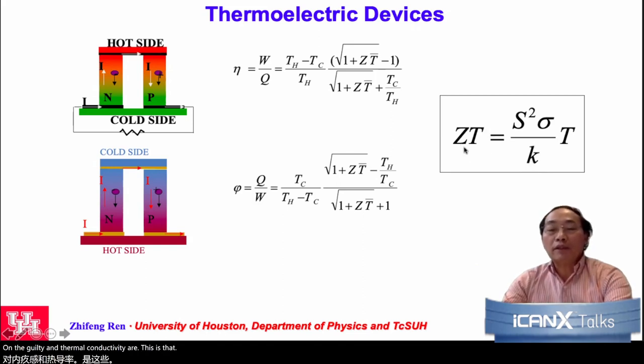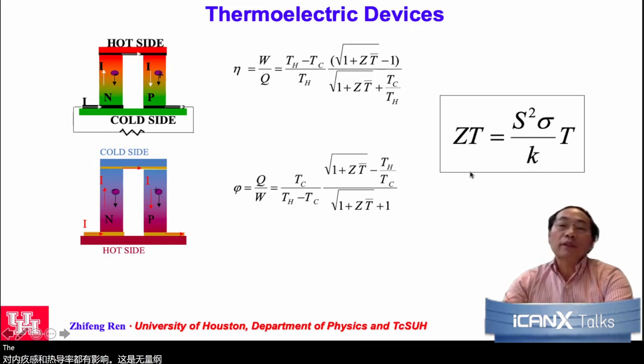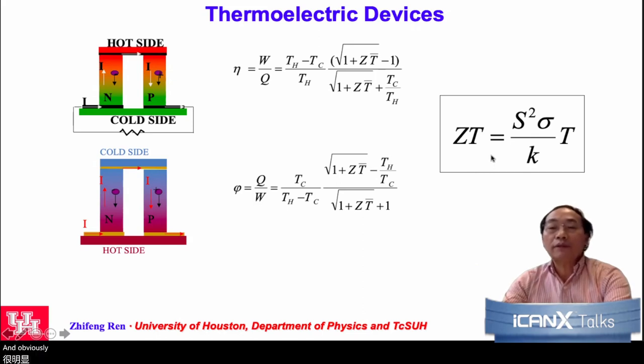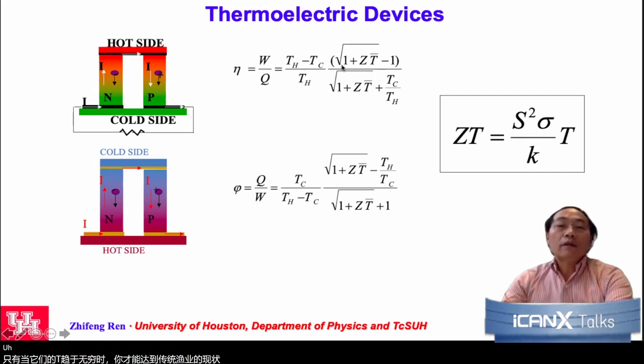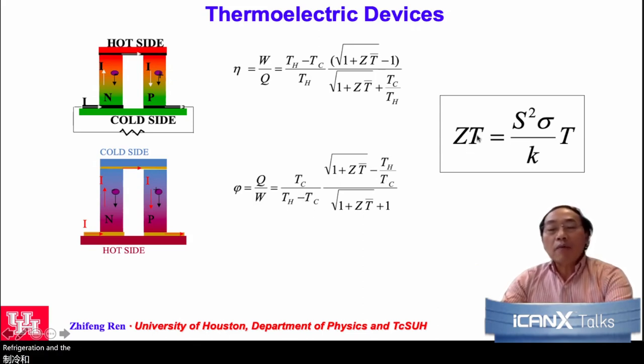This is dimensionless with the temperature there. And obviously, as you can see from the efficiency formula, only when ZT goes to infinity do you reach the Carnot efficiency of the traditional heat engine or the cooling refrigeration. And obviously ZT, so far, is not an infinite number, but a very small number.